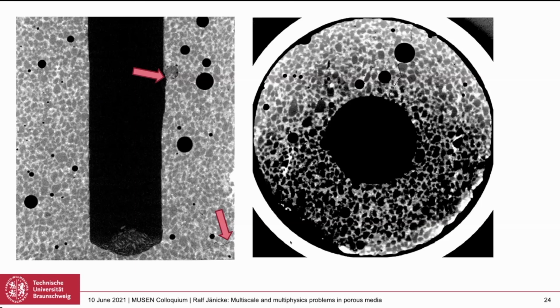And this is very fresh data that's not much made of. That's just the raw data we see here. So this is a concrete tube which has a diameter of roughly 8 millimeters. And there's a borehole here. We drilled the borehole with a diameter of 3 millimeters, and this is filled with water. We are at the moment not really sure yet how it penetrates the concrete, that's too early to say. But we were interested in what happens in this borehole.